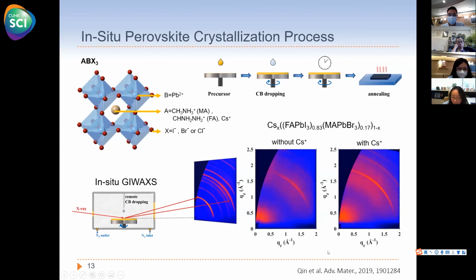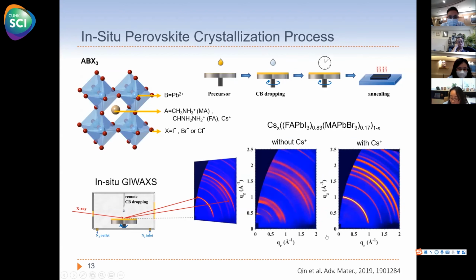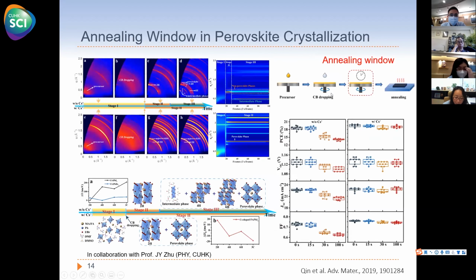So here are two videos showing two systems, one with cesium, one without cesium, and you can see how the GIWAXS pattern evolves, and they are undergoing very different crystallization pathways. Then after we look into the detail, we can see the system without cesium undergoes 3 stages of crystallization, and the system with cesium only undergoes 2 stages of crystallization.